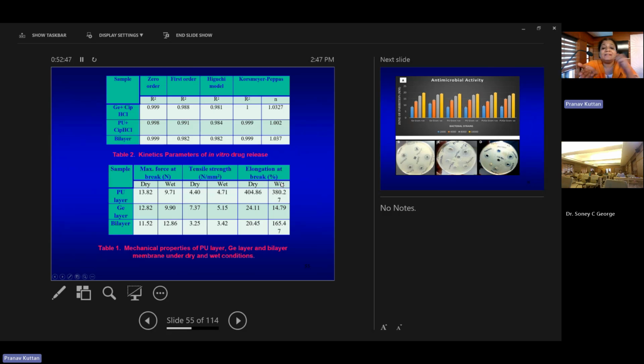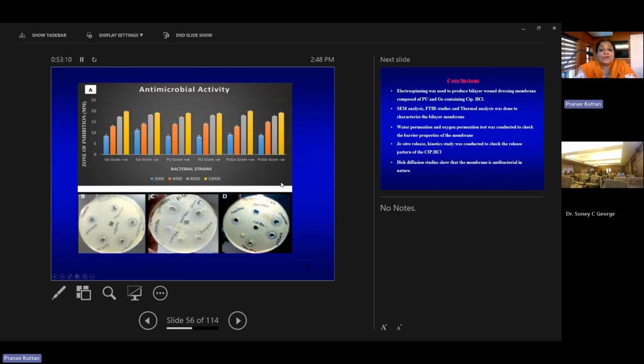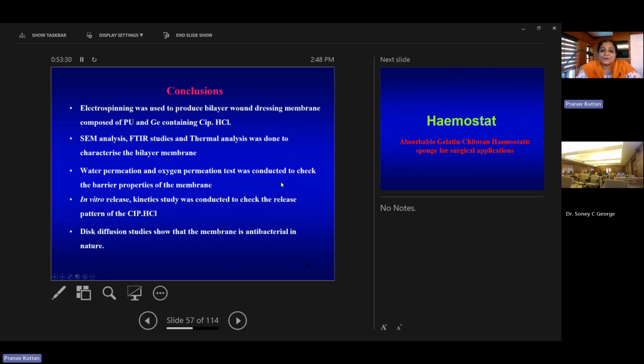So what we thought was that when it is in the dry condition, it doesn't have much elongation, so the value is low. Whereas when it is in the wet condition, because of the presence of gelatin and polyurethane, the combined synergistic effect increases the value to 165.47. And again, since we are planning it for wound healing, we tested the antibacterial activity on different gram positive and gram negative organisms at different concentrations, and we found a considerable zone of inhibition, which indicates that it is a good antibacterial material.